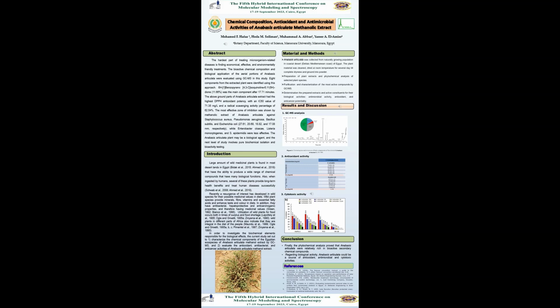Based on the IC50 values, the aqueous extract of Anabasis articulata has an antioxidant activity of 33.64 mg per milliliter. Cytotoxic activity. The significant cytotoxic potential of Anabasis articulata having IC50 values of 62.35 micrograms per milliliter for HEPG2 cell lines, 73.64 for MCF7 cell lines, 61.34 for PC3 cell lines, and greater than 100 micrograms per milliliter for normal cells.